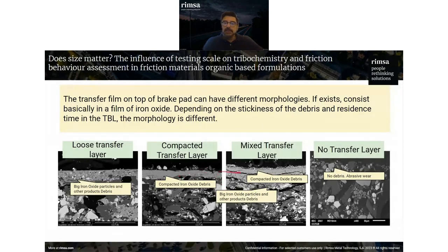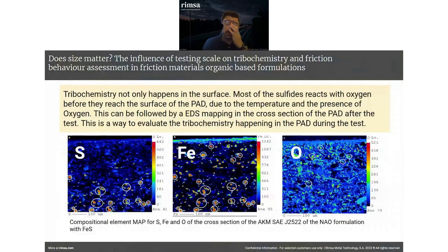This can be the mixed transfer film, so we have some areas that are compacted debris, some areas that are loose debris, and we may also have the possibility of not having any transfer layer on top of the brake pad. Sometimes, depending on the formulas, you don't get this thick or thin transfer film. But tribochemistry happens not only on the surface, it also happens beneath the surface. We may have some additives, some chemicals in the composition, like the phenolic resin, or other additives that may be reactive to the environment where the friction takes place.